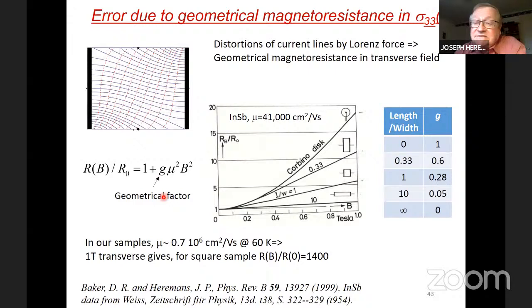Now, let me point out first and foremost that we can use this to get an idea of the error, but we cannot use this to correct our data quantitatively because this model is of course extremely primitive. For one thing, we have a mobility that's probably field dependent, besides which we cannot define the mobility because we don't have a mass. It's a concept we don't have in Weyl semimetals. We only have a velocity and a scattering time. So this model really doesn't apply. We cannot use it to do any physics with, but we can use it to get the order of magnitude of the error. And the order of magnitude, whether it's 1% or a factor of 1,000, is all that really matters.